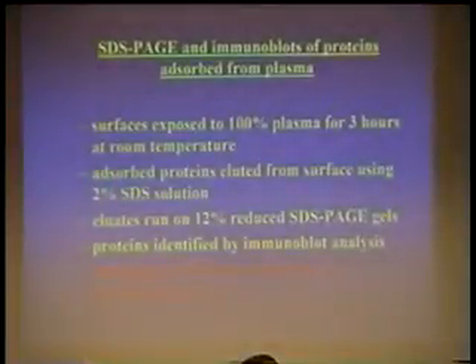We've also looked at other proteins in plasma, and this allows me to introduce one of our other techniques that we use in blood systems or plasma systems, and that is to do this, where we expose the surface to plasma, and then we elute the adsorbed proteins using a detergent, in this case SDS, and we take the eluted proteins and we run them on gels and identify the proteins by immunoblot analysis.